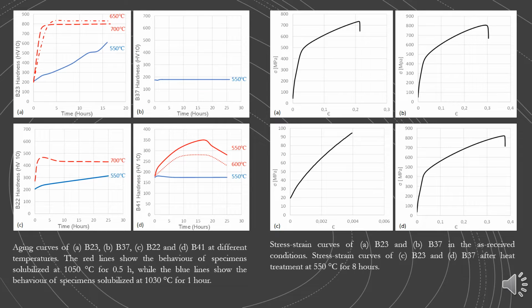Here on the left, the specimens were subjected to aging at 550 to 700 degrees Celsius after solubilizing at 1050 degrees for half an hour, shown by the red line, and after solubilizing at 1030 for 1 hour, shown by the blue line. It can be seen that the alloys B22 and B23 show an increase in their hardness while B37 and B41 remain almost constant. This behavior is due to the higher quantity of aluminium in B22 and B23.